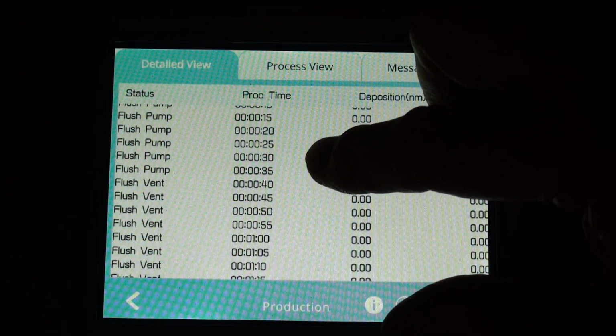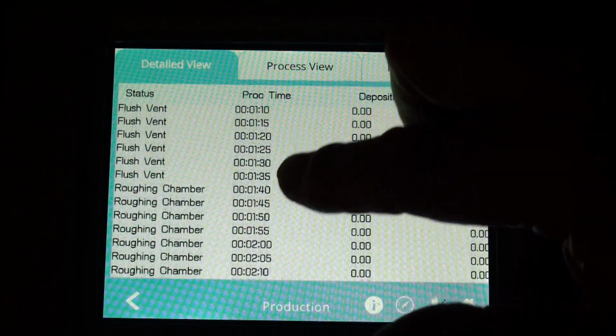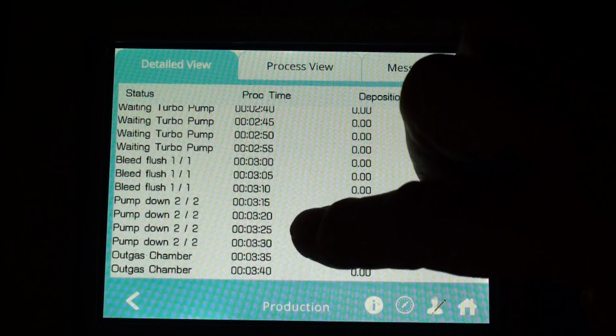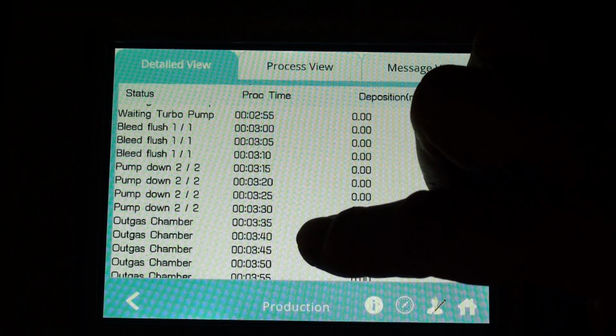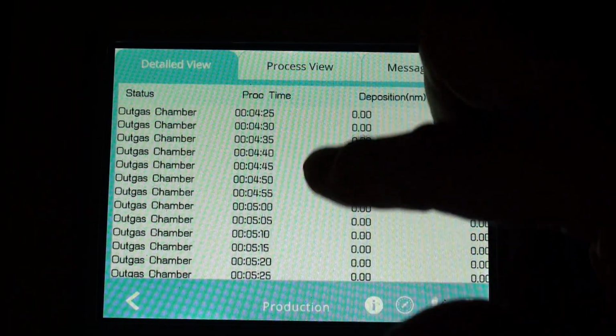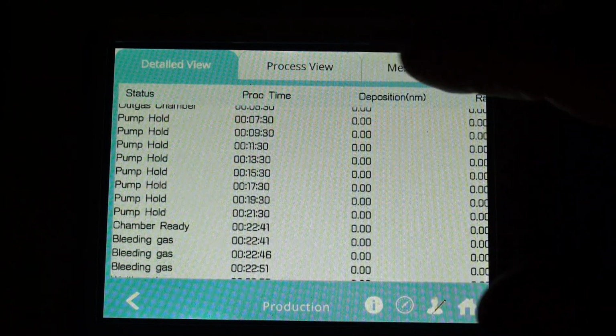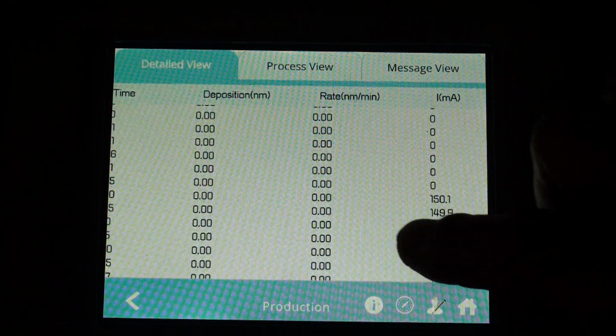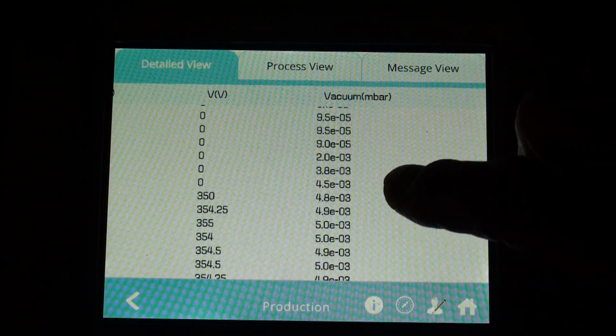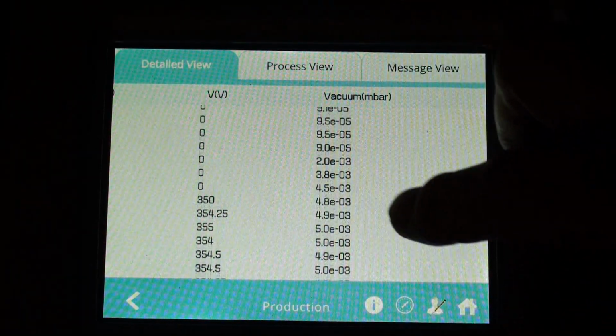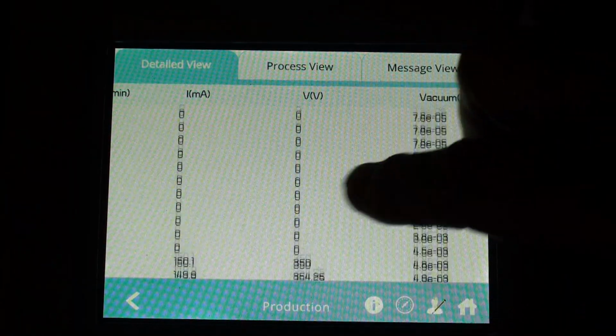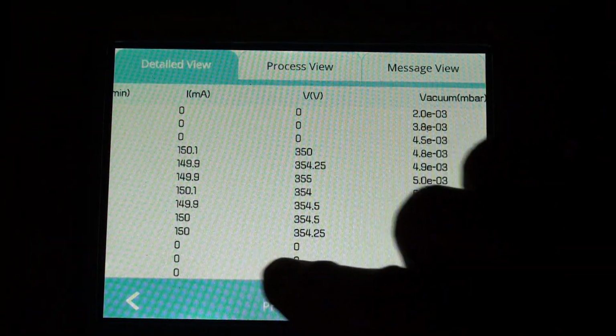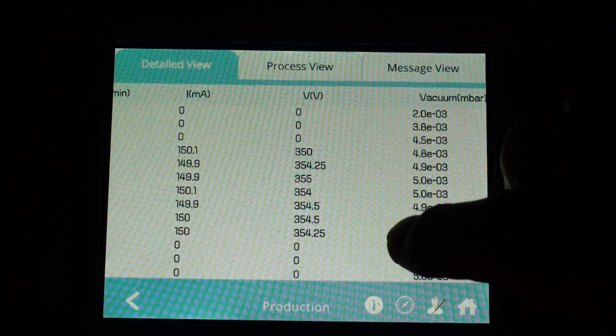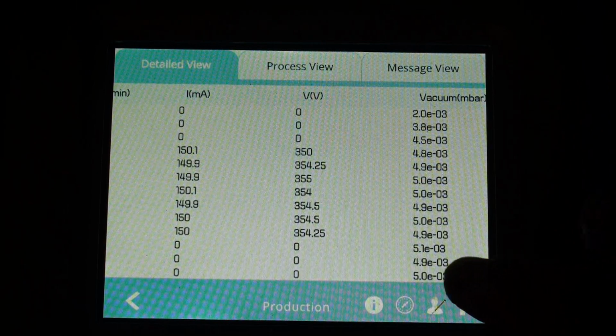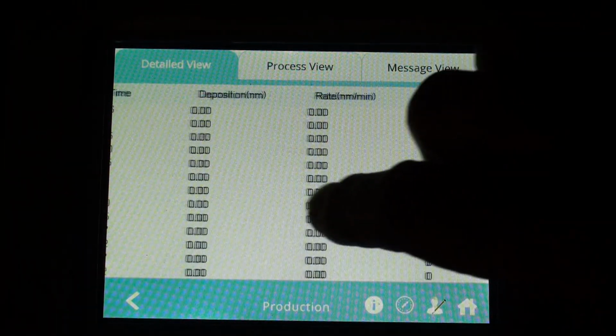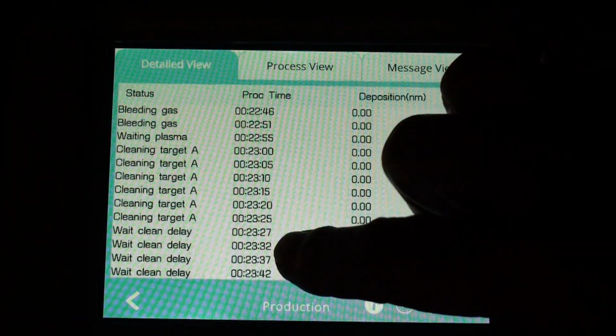It clears the backing, flushes the system, vents, roughs the chamber, waiting on turbo pump, bleed flush, this process time, pump down 2, outgas chamber. All these are to get rid of any residual gases in the chamber. Over here it shows you the vacuum achieved, and then it shows cleaning target and the voltage and currents involved in that. 350 volts approximately at 150 milliamps, so that's cleaning target.